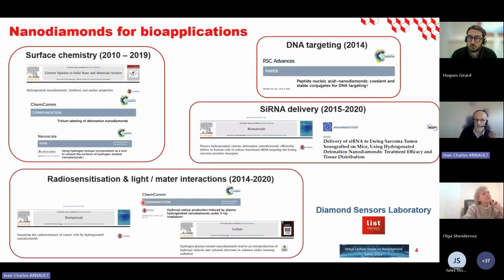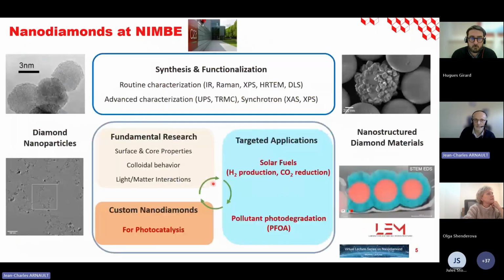In parallel, we evidenced some interesting properties of nanodiamonds, which could be active under X-ray or gamma ray irradiation, especially active in producing some radicals in water, for example, hydroxyl radicals, or even scavenging those radicals if you change the nature of the particles. Five years ago, we moved to a new laboratory at CEA, as Olga said before. So our goal today is really to go on with the control of the particles, their surface and their core properties, to link that with the colloidal behavior of these particles, and also always motivated by specific interaction between light and nanodiamonds.